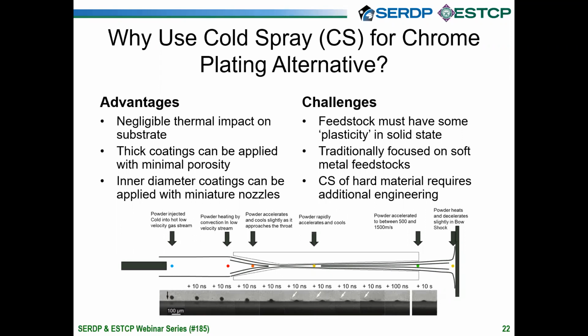So there's a lot of reasons why we would want to use cold spray for a chrome plating alternative. But one of the challenges is that chrome plating is a very high hardness material, and it can be challenging to get very high hardness cold spray coatings. The reason for that is because we need some plasticity in the solid state of the metal feedstock material so that we can successfully build up a dense coating. Traditionally, cold spray is focused on metal feedstocks, and cold spraying hard metals or ceramics requires additional engineering.